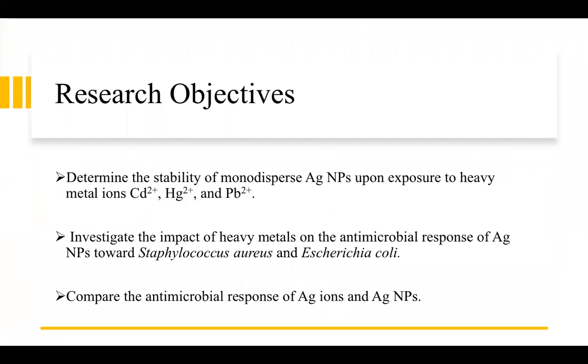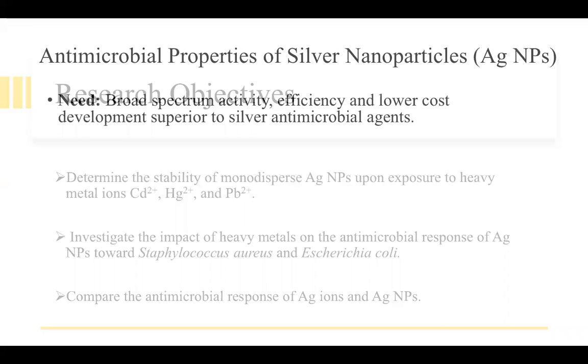So here, our research objectives were to determine the stability of monodispersed silver nanoparticles upon exposure to heavy metal ions: cadmium, mercury, and lead. We also investigated the impact of heavy metals on antimicrobial response of silver nanoparticles towards gram-positive Staph aureus and gram-negative E. coli. And then finally, we compared the antimicrobial response of silver ions and silver nanoparticles, as a lot of times the toxic response of silver nanoparticles is expected to come from silver ions. We wanted to see if there's a difference in the behavior that we saw as that occurred.